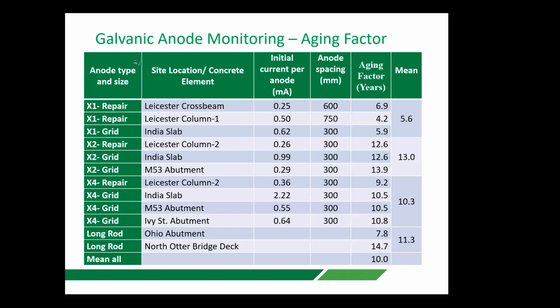And that early forcing of the anodes to deliver a high current has not allowed the corrosion products to migrate into the pore structure sufficiently quickly. So they started to block the interface between the zinc and the mortar. And that induced a reduction in the current output, which resulted in a lower aging factor.